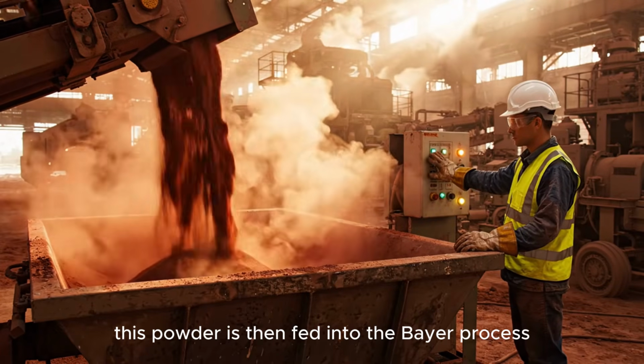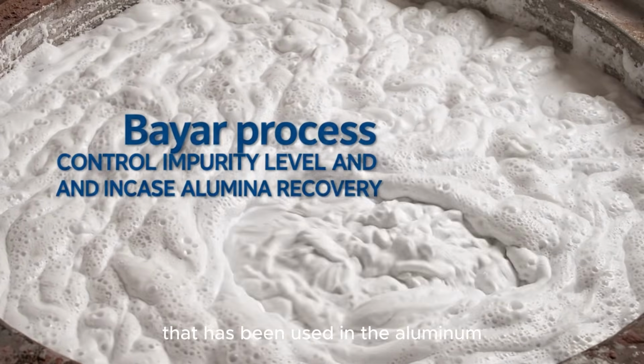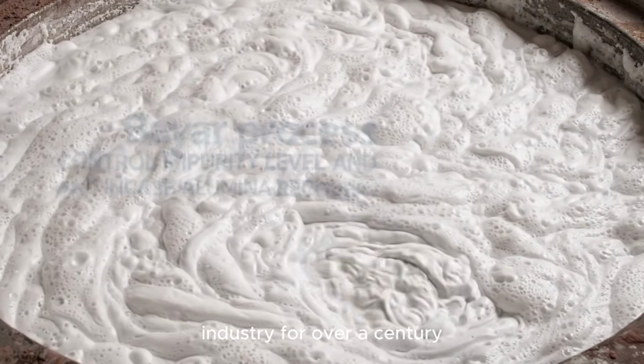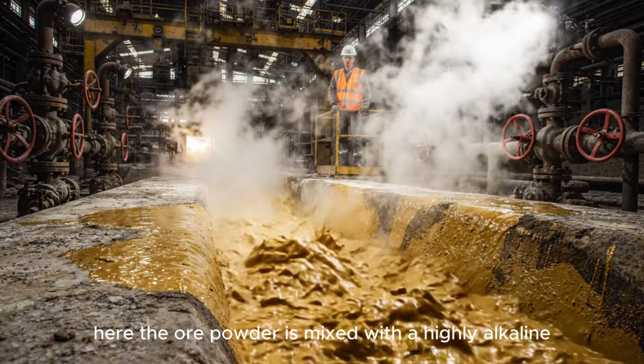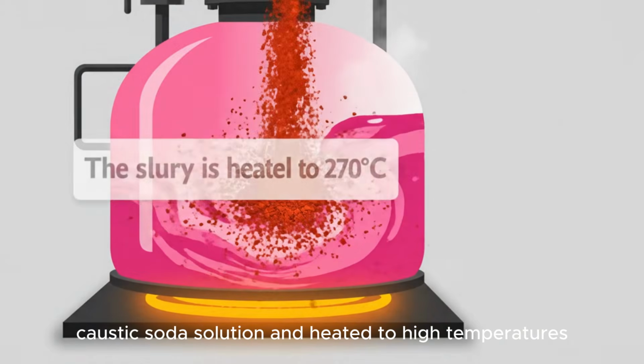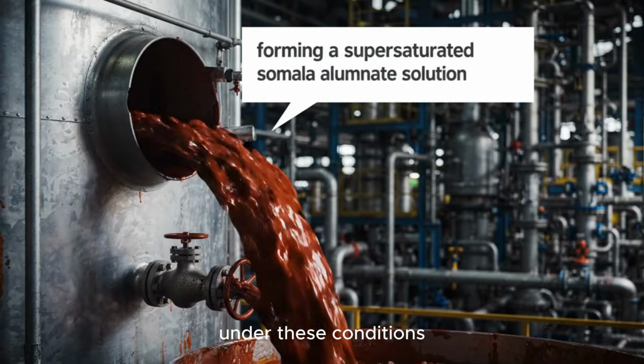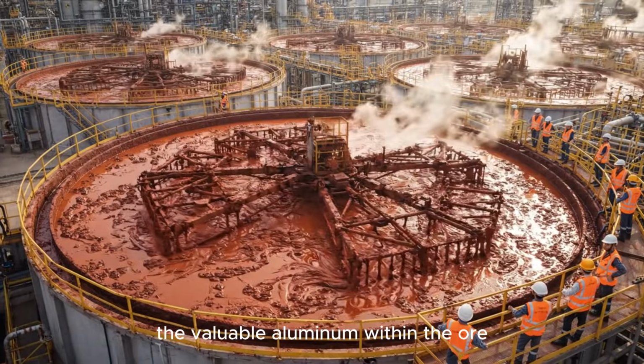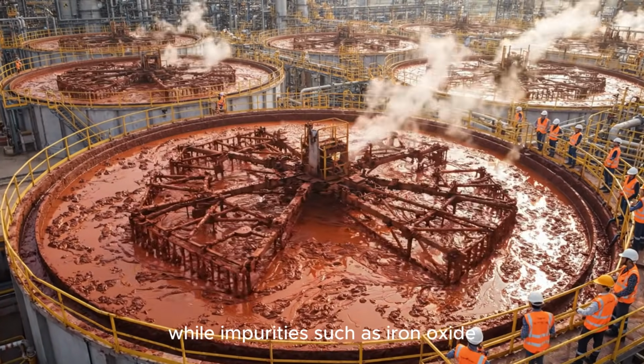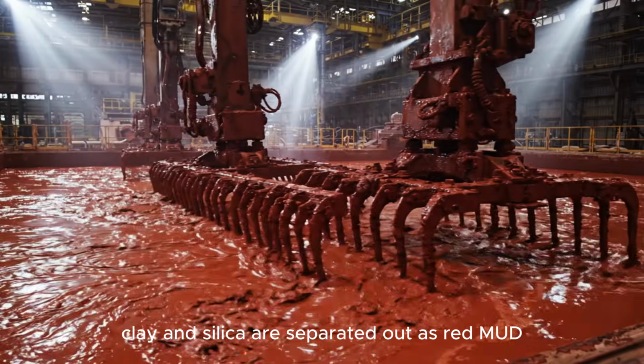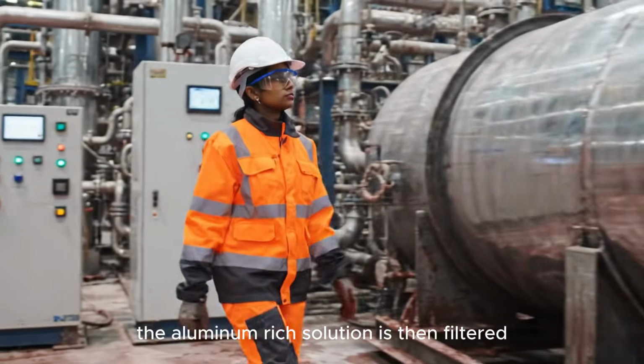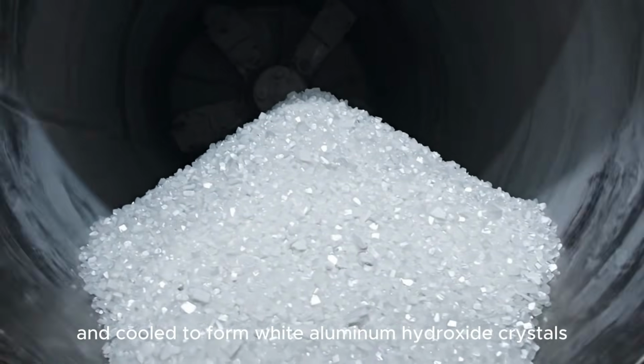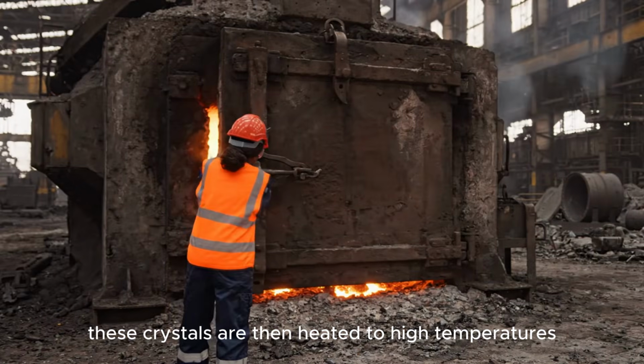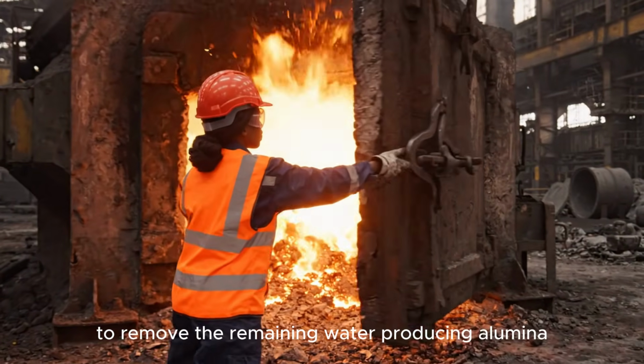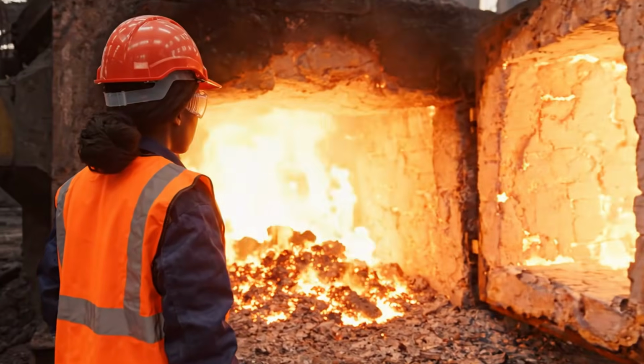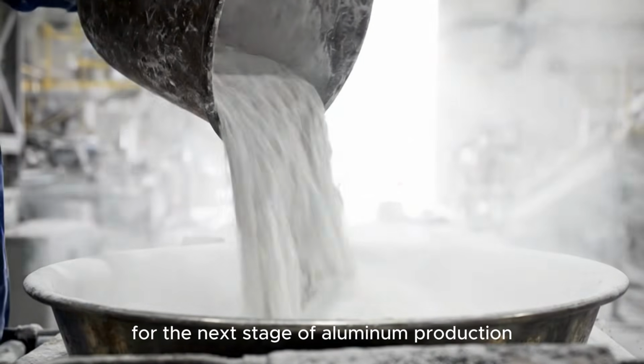This powder is then fed into the Bayer process, a refining technology that has been used in the aluminum industry for over a century. Here, the ore powder is mixed with a highly alkaline caustic soda solution and heated to high temperatures. Under these conditions, the valuable aluminum within the ore dissolves into the solution, while impurities such as iron oxide, clay and silica are separated out as red mud. The aluminum-rich solution is then filtered and cooled to form white aluminum hydroxide crystals. These crystals are then heated to high temperatures to remove the remaining water, producing alumina, a pure white powder that will become the raw material for the next stage of aluminum production.